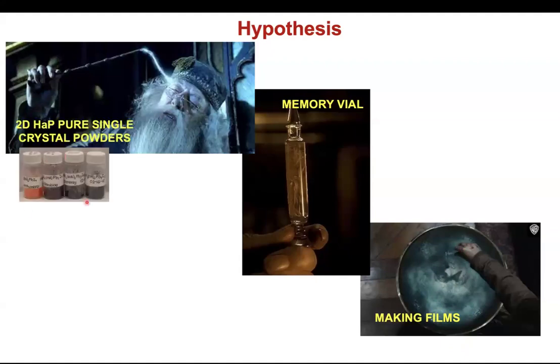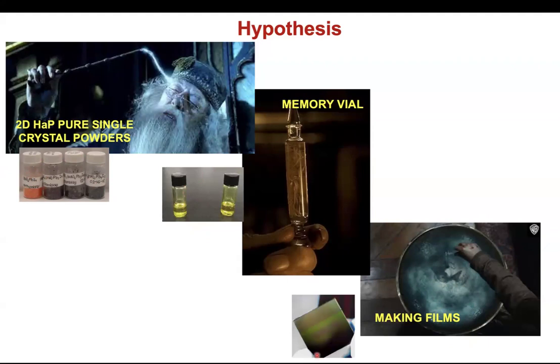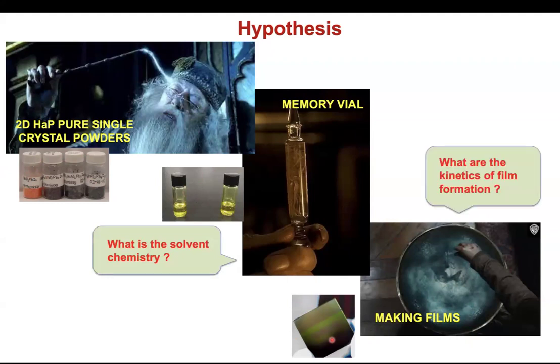You were taking these 2D perovskites, these crystals. There's N1, 2, 3, and 4. You were dissolving that into the solvents, and then you were making films of this material. Okay. So this was kind of what came to us, and this led us to a hypothesis of what's really happening. What's happening in the solvent that allows us to get these films, and what are the kinetics of this filmmaking process? How are they different compared to what people have been doing? Okay.